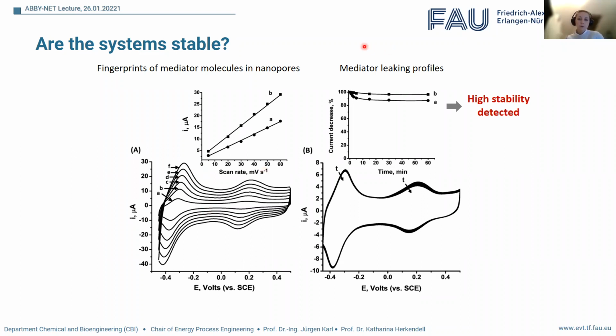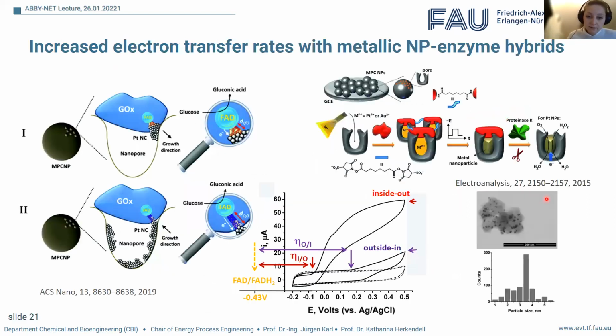You can see also here a leaking study over time, where you could actually see that over the time of 60 minutes here, we would actually initially lose a little bit of mediator molecules, but that after a certain starting time, we had very stable systems for enzymatically stabilized systems that would give us very incorporated designs.